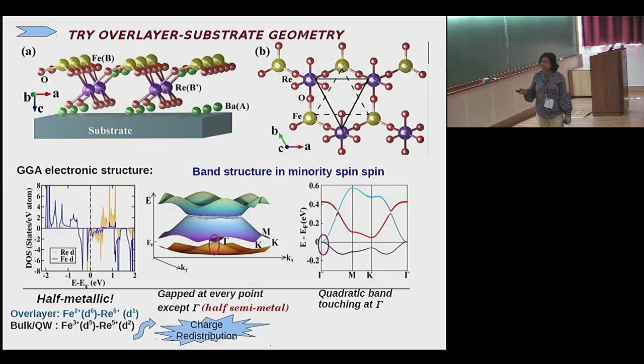And the second important thing that happens is that there is a charge redistribution. In the bulk or quantum well structure, the iron was nominally 3+ and rhenium was 5+, so a d5, d2 kind of combination, while in this overlayer it became iron d6 and rhenium d1 configuration. So therefore, these 3 bands, instead of being occupied by 2 electrons, now become occupied by a single electron. And this is basically the electronic structure in the absence of spin-orbit coupling.